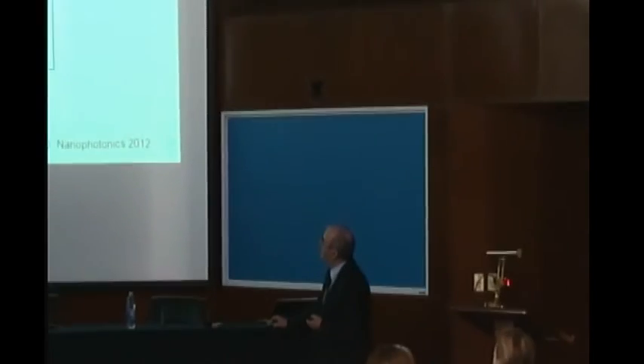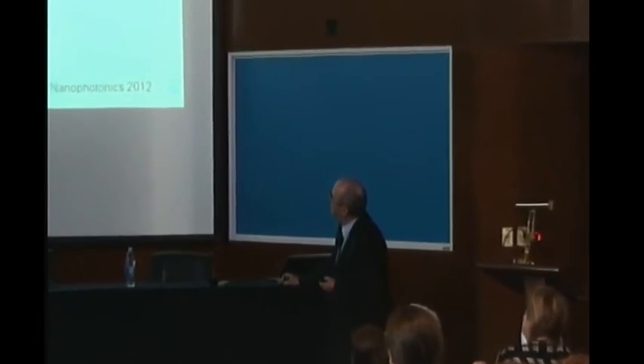And now we can follow through the luminescence only one dot. What you can see here is the fluorescence as a function of the temperature. It's only one dot. What you can see is that one dot, a 30 nanometer dot, may show you a hysteresis loop. That means that you can measure the property of a 30 nanometer dot, and it shows a hysteresis loop.